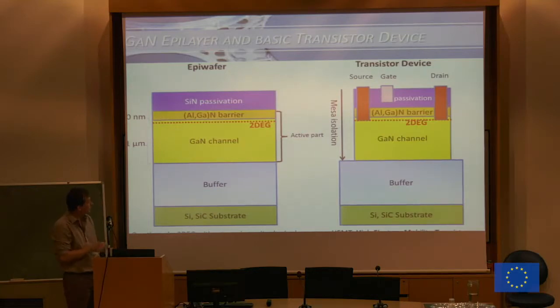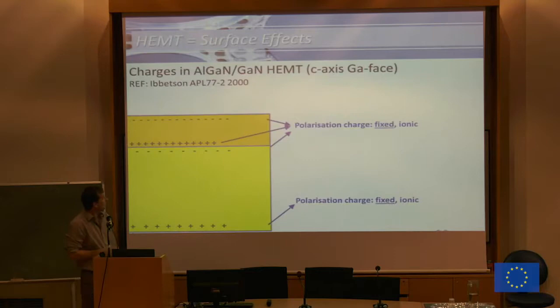Now, with such a structure, you can make the lateral device. What you need is two ohmic contacts to contact the two-dimensional electron gas, and a gate in between to modulate the current in between the two. Now, one important aspect, I think that was also pointed out yesterday, is that we have these polarization charges that are larger in the aluminum gallium nitride than in the gallium nitride.